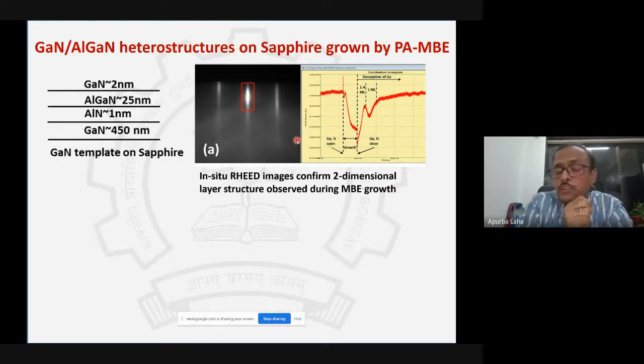Now, it so happens that when the surface is enriched with gallium metal... if you look at the gallium nitride crystal, you have 1:1, 50% gallium, 50% nitrogen. If you bring 50% gallium and 50% nitrogen onto the surface, then you may not be able to succeed in growing the two-dimensional layer. That's because the diffusion of gallium adatoms on a nitrogen-rich surface is much lower than if the surface is gallium rich. That means the surface should be a little metal rich.